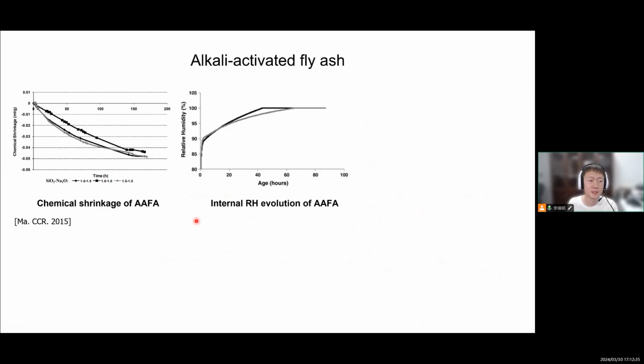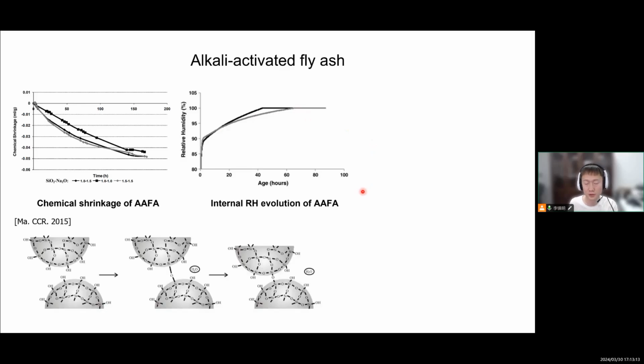So anyway, I want to say that even though there is chemical shrinkage of alkali-activated fly ash, and also for the alkali-activated metakaolin, the relative humidity inside the system didn't really decrease. It actually even increased because of the consumption of ions. As we know, the relative humidity of salt solution is lower than water. So when the ions are consumed, the relative humidity can increase. And because there is no self-desiccation, the relative humidity can be even closer to 100%. Which means that the shrinkage is not caused by the same mechanism as in Portland cement.